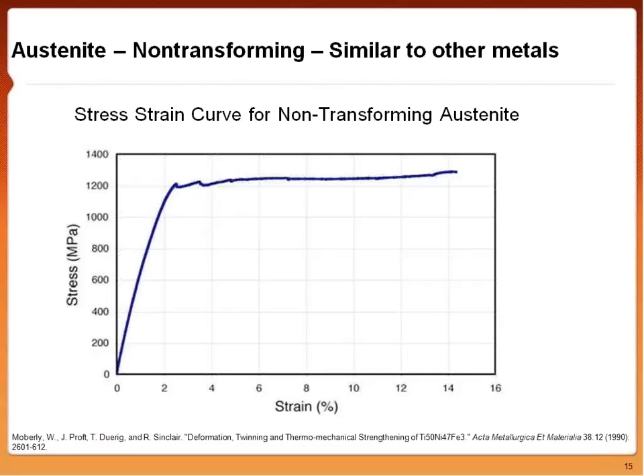The ordered crystal structure produces a stress strain curve that is similar to most other metals. The interesting thing about the austenitic stress strain curve for nitinol is that it actually has a very low elastic modulus compared to similar steels that operate in this behavior where they have very little strain until yielding. Nitinol has a very low yield point and then quite a long work hardening rate.